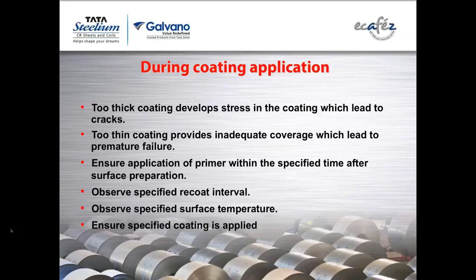Now ensure application of primer within specified time after surface preparation. That is what we have discussed. Then observe specified recoat intervals. Now these recoat intervals are also very important. Some have, say, 6 hours at so much of ambient temperature to 36 hours max. If you do it beyond, usually epoxies we prefer because they have very good chemical resistance, very good corrosion resistance, very good water resistance, etc. This epoxy after full curing is not going to accept the further coat. That is why it gets blocked. So naturally they say that you apply before certain time, before it completely polymerized, and otherwise you will not get